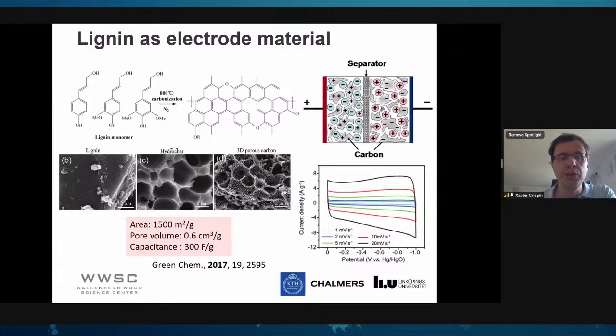There's also the potential to use the fact that lignin is very amorphous, to introduce porosity and nanoporosity. So you can, for instance, obtain by different treatments carbon material from lignin that has a surface area of 1,500 square meters per gram. So it's a very large surface area. And then you can use it as an electrode in a supercapacitor. So you put in your electrolyte and then you just charge, and you see that it's like a square box. So it is a supercapacitor type. And the capacitance is about 300 farad per gram, which is quite decent, I would say. So a very cheap material and quite good charge capacitance in that case.